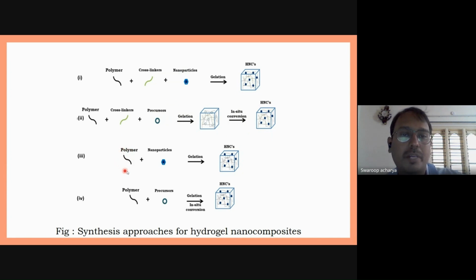Coming to the third method, here we take the aqueous polymers and the prepared nanoparticles, we add them, and the gelation will be done, and the final product will be ready. This gelation technique is a radiation cross-linking technique. In the final method, the polymer will be there, and precursor materials for the reduction to nanoparticles will be added, and the gelation as well as the in situ conversion can both be done in a single step, and finally the hydrogel nanocomposites can be formed.